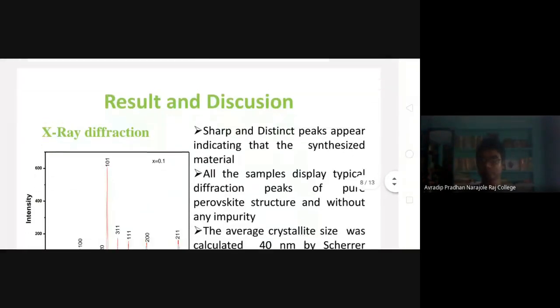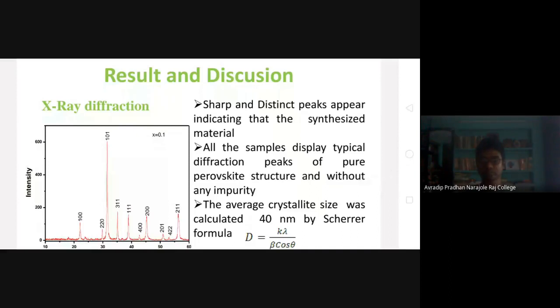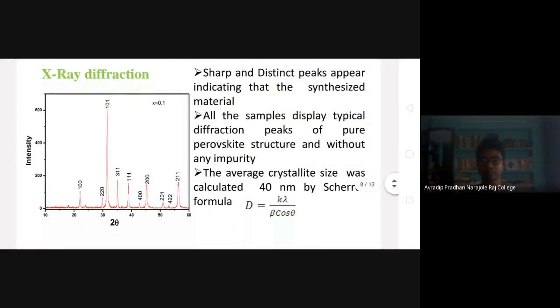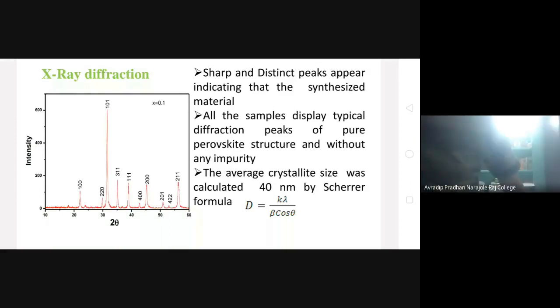These are the results and discussions. In this slide, we have shown the X-ray diffraction, where sharp and distinct peaks appear, indicating a very well synthesized material. All the samples display the typical diffraction peaks of a pure perovskite structure, without any impurity. The average crystallite size is calculated to be 40 nanometers, using the Scherrer formula, which is K lambda by beta cos theta. Beta is the full width at half maxima.